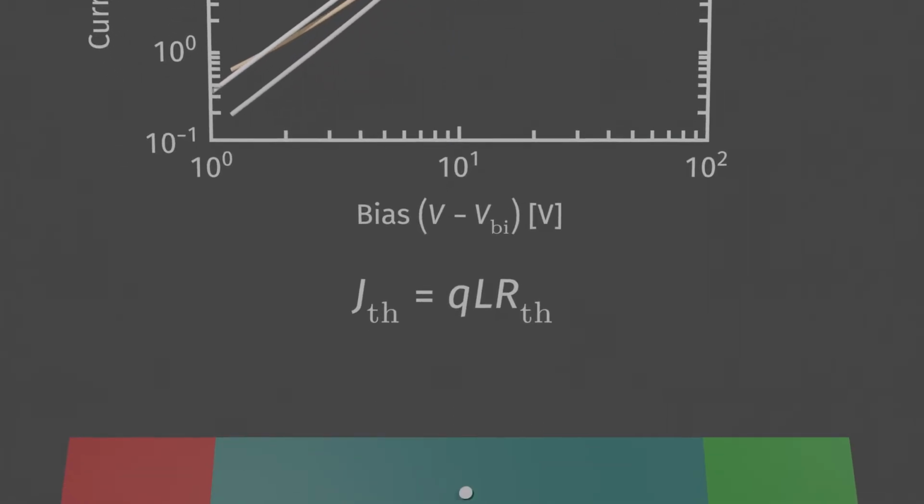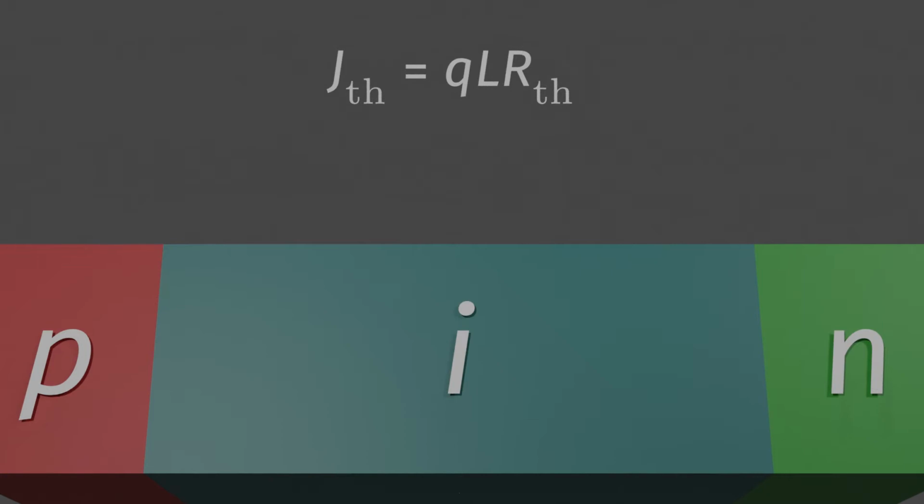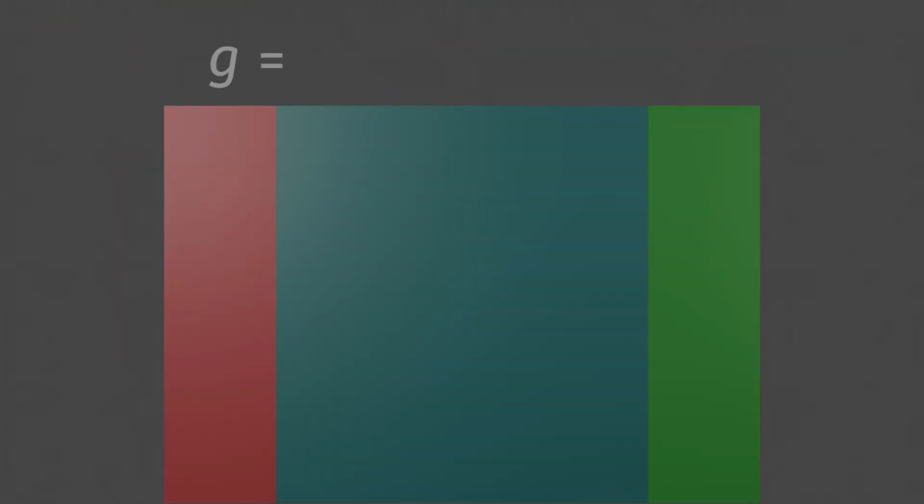Looking at the important parameters for biasing and thermal management, the current threshold depends on the length of the device and the rate of electrons recombining with holes for lasing, which is really just a statement of particle conservation and balanced charge injection. The voltage follows from the Mott-Gurney law. The next step is to work out the required recombination rate, which means we have to work out how many singlets are needed.